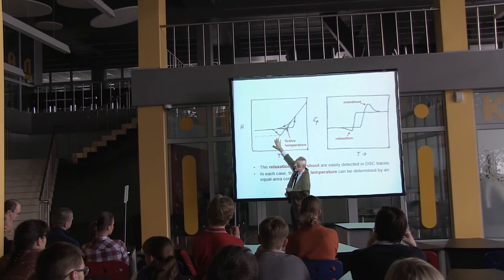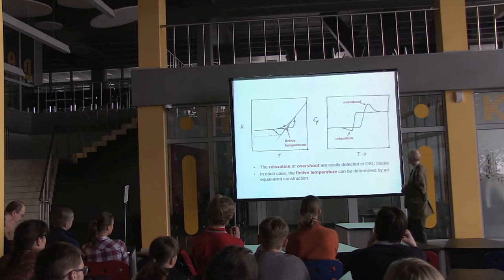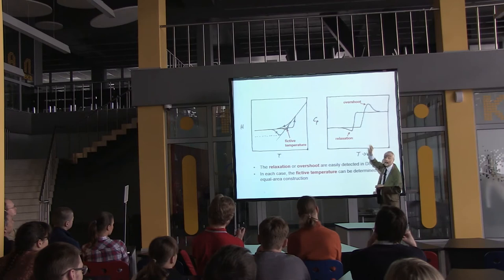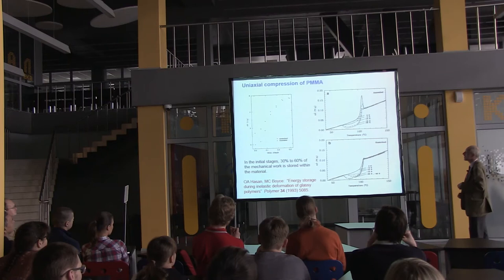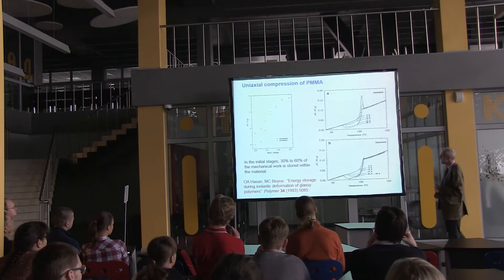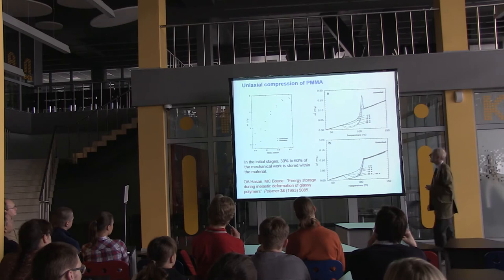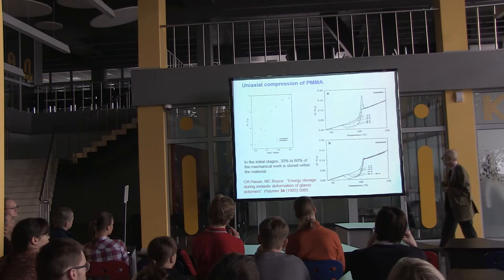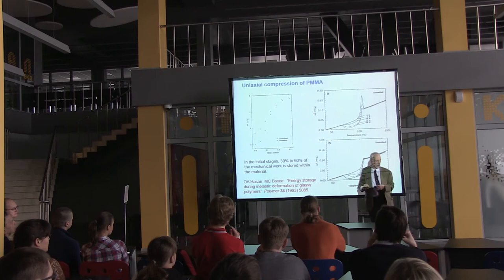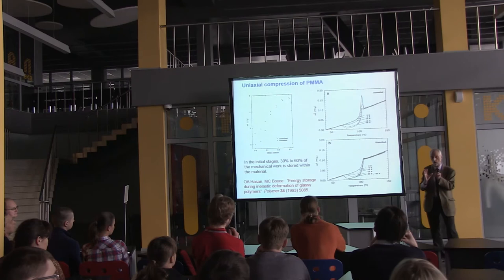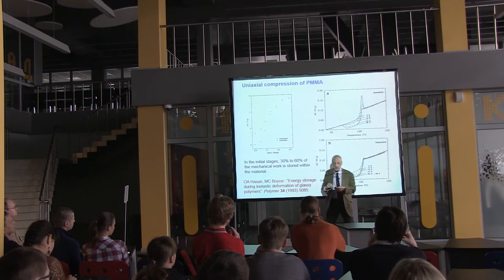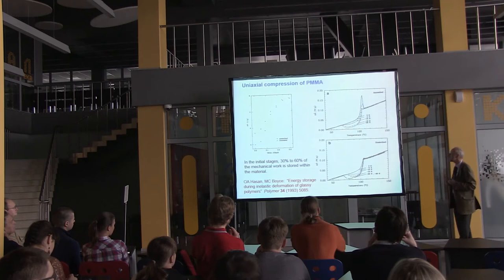For a glass made of PMMA — polymethyl methacrylate — which is a high-quality cast polymer, the initial state is rather relaxed. When you heat it you see that overshoot peak, that sharp spike. If you take that PMMA sample and plastically deform it, doing mechanical work on the system, you push the polymer towards a higher energy state. When you then heat it you see a heat of relaxation — quite a large heat.